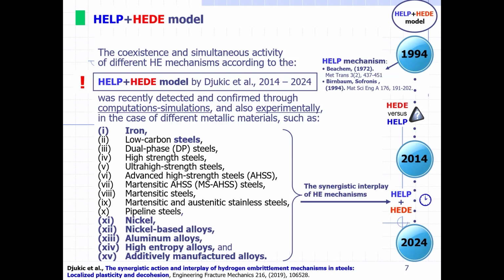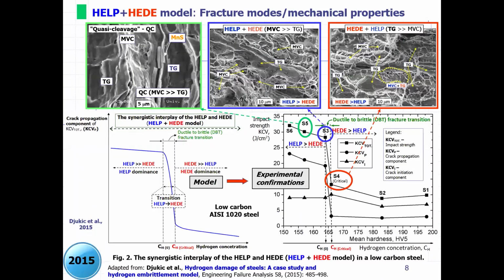including low carbon steel, high strength steel, martensitic steels, pipeline steel, but recently it is also applied and confirmed that it's operative in nickel-based alloy, aluminum alloy, high entropy alloy, and additively manufactured alloy. So I will give you some new results.